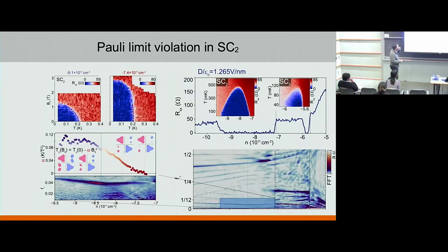And the way we explore this is that within this region, you can do a different experiment. You can plot your TC as a function of the in-plane magnetic field, and you can try to fit these curves with some kind of second-order polynomial. And the idea is that when you are in this regime of SC2, everything fits relatively nicely with TC is TC0 minus the magnetic field squared, some kind of quadratic term.